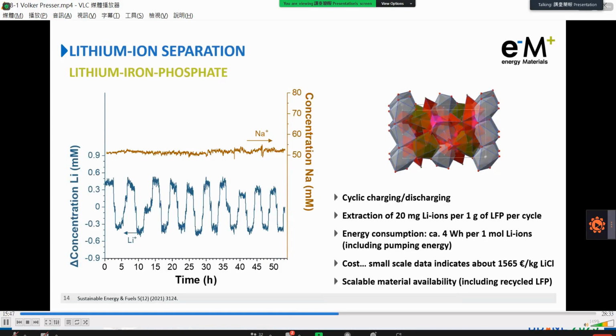Indeed, the extraction capacity is about 20 milligrams lithium per 1 gram of LFP per cycle. This comes down to an energy consumption of around 4 watt-hours per mole of lithium ions. And this includes a modest estimate for pumping energy. However, if you really want to extract more precise data, a much larger prototype will need to be developed and built to more realistically benchmark the energy uptakes. That also pertains to costs.